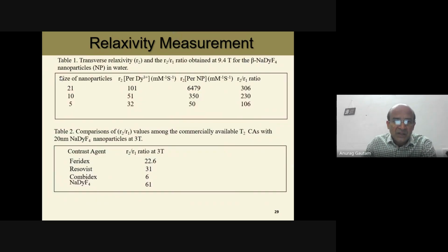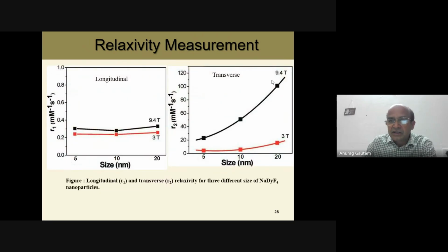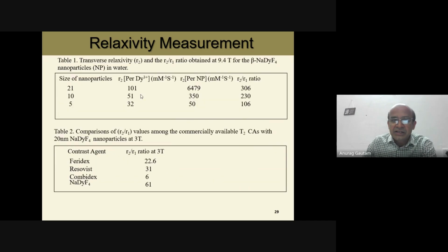Look at here. For a 20 nanometer particle, R2 for one dysprosium is 101. This is for one dysprosium that we are measuring. So this is 101. If you go per nanoparticle, this is very, very high, 6,479. And the ratio, R2 by R1, is 306. And if we compare with the commercially available contrast agents, which are Feridex and Resovist, this number is very high. This is 306. The commercially available contrast agents are only 22 or 31. So this is very, very useful for imaging applications.